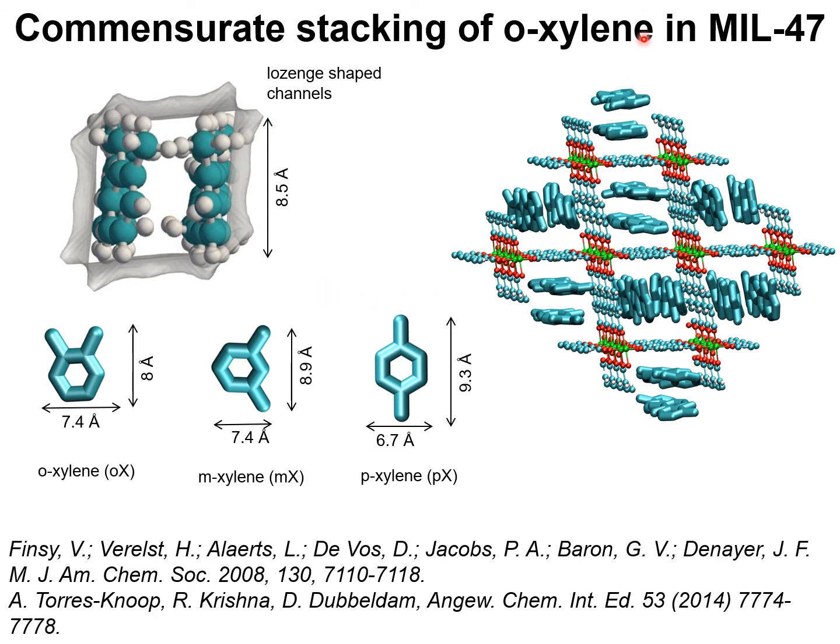Within the one-dimensional channels of MIL-47, that is channels of 8.5 angstrom that are lozenge shaped, orthoxylene can be stacked because the dimensions are commensurate with the channel dimensions.